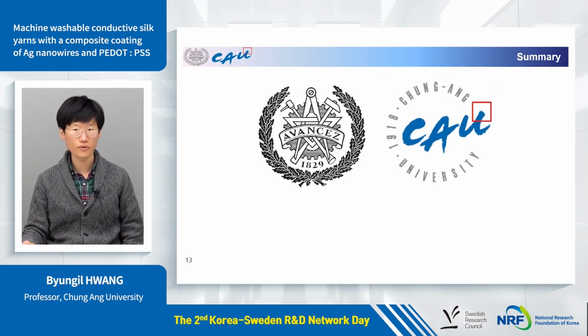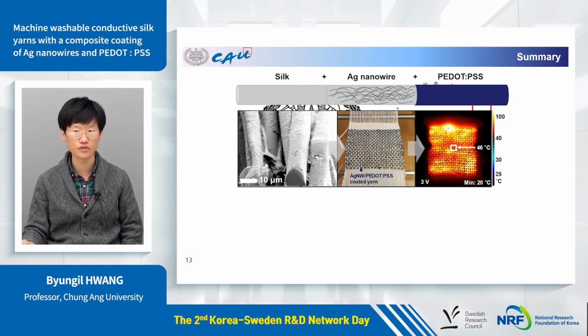So, in summary, as a result of collaboration between our team and Prof. Miller's team at Chalmers, we could develop machine-washable, highly conductive silk yarns using a silver nanowire and PEDOT:PSS composite coating. Our fibers really show high electrical conductivity, as well as excellent machine washability and mechanical reliability. We believe our development will help to accelerate the commercialization of robust wearable electric devices.